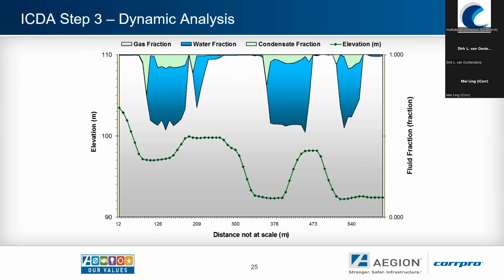And so when we ran the model and then turned on the composition tracking, we could actually start to see the gas fraction, the water fraction, and the condensate fraction as to where we would have water dropping out. And so it becomes rather visual. You can see where the water is the highest concentrations. So at about 126 meters down the pipeline route, you'll see that there's a large area of water that's potentially being trapped there. But moving over to around 209 meter, you'll also see a peak there. So there is some carryover that gets trapped at the top at that plateau.